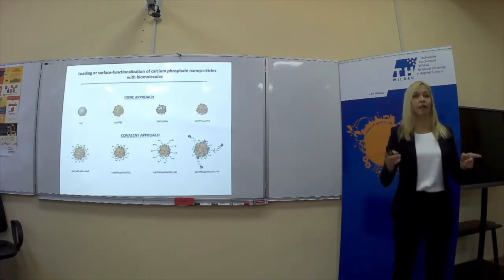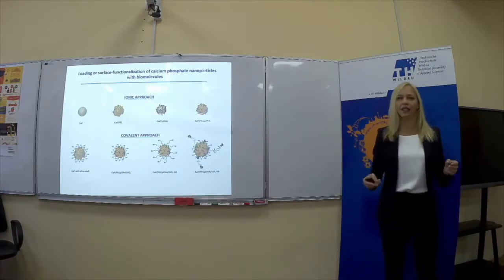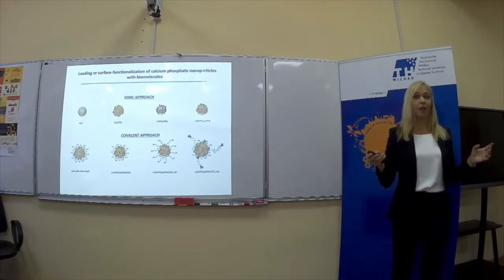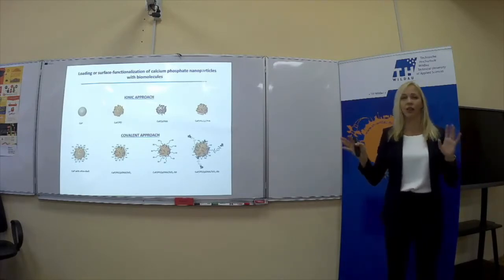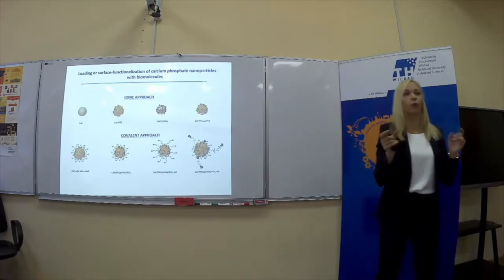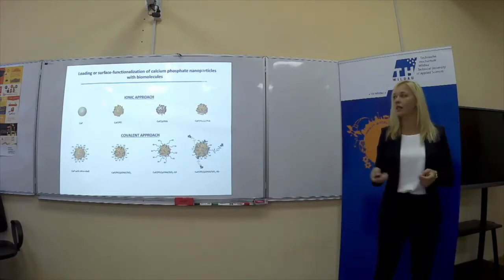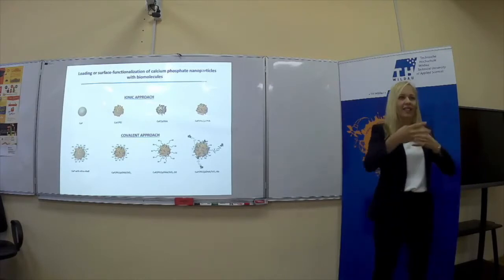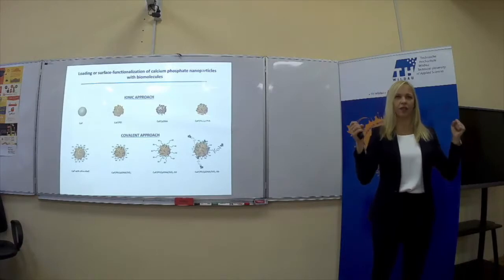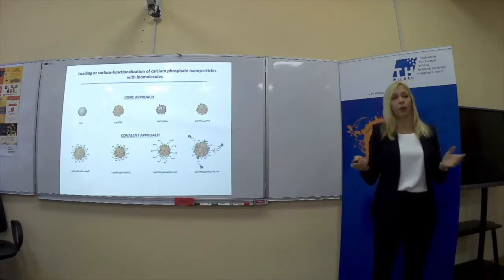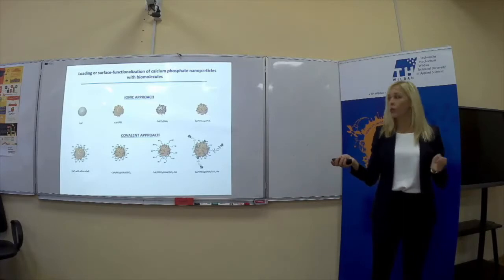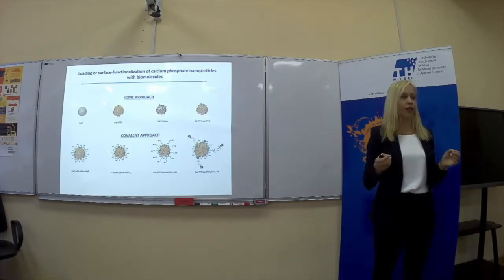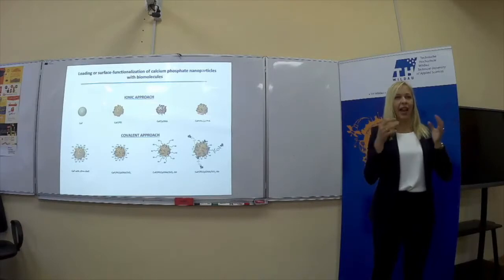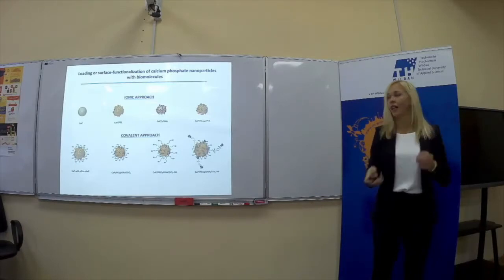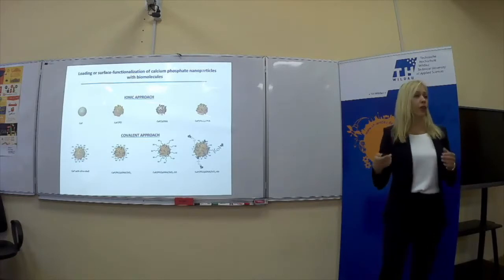The main problems exist when you start to work with bigger biomolecules. For example, you want to attach antibodies to these particles. This nanoparticle is around 100 nanometers, and an antibody is also pretty big, comparable, like 5 nanometers. And electrostatic interaction is not enough to keep antibodies on the surface. We were thinking, what can we do to attach such antibodies to the surface? Of course, the best attachment is covalent binding, but with calcium phosphate, you cannot do it.